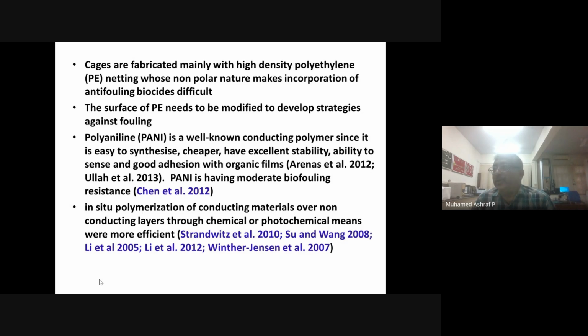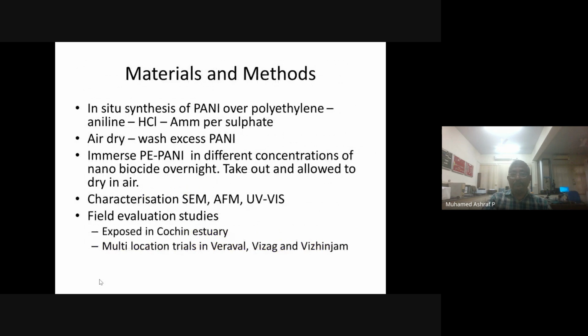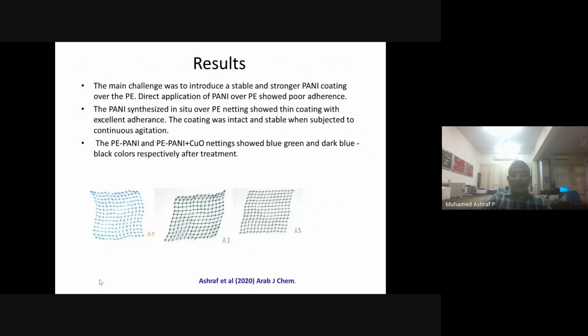Then we thought to synthesize it in situ. That means we dip the aquaculture cage nets in aniline solution, and then polymerize the aniline to become polyaniline. During the formation, the polyaniline will be attached over the net, so that we get a very uniform coating of polyaniline, and it will look like this.